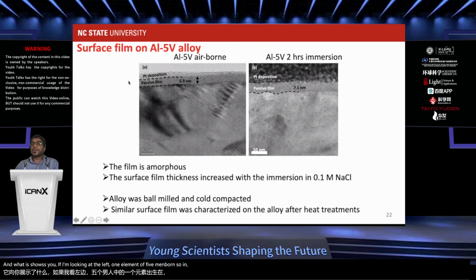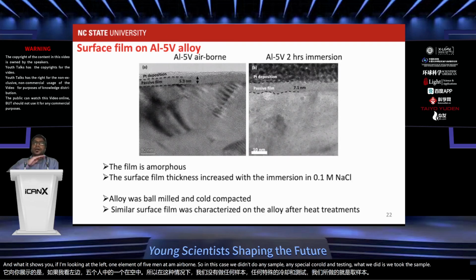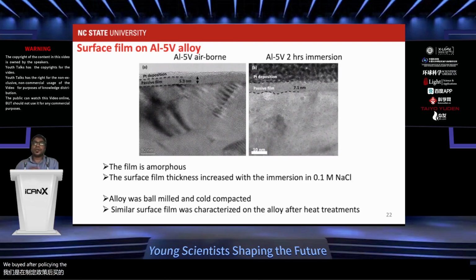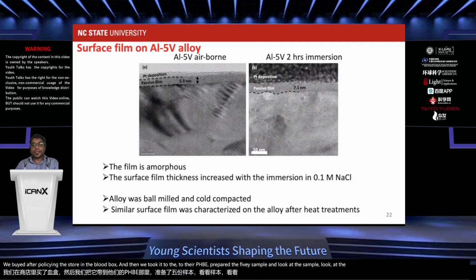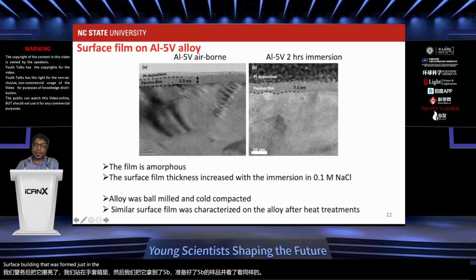So in this case, we didn't do any special corrosion testing. What we did is we took the sample, we polished it. After polishing, we stored it in the glove box, and then we took it to the FIB, prepared the FIB sample, and looked at the surface film that was formed just in the air, right? So we see a 5.3 nanometer thick film.